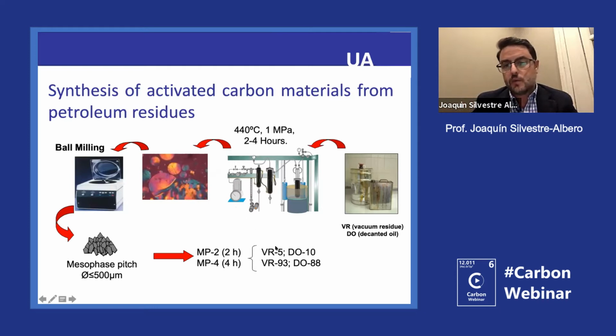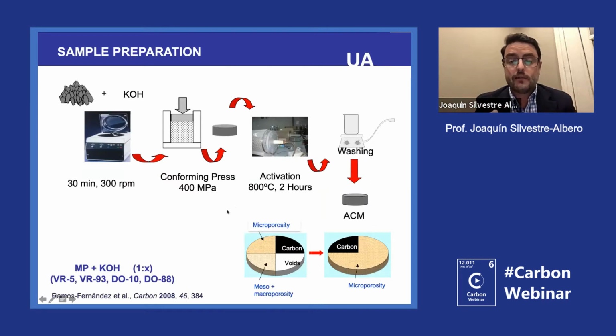So at the end, we were able to obtain residues with a low mesophase content, in this case VR5, that means 5% of mesophase, or changing the time conditions, we were able to go to high mesophase content. So we were preparing samples like, for instance, VR93, where you have 93% of mesophase. So basically what we were doing is changing the microstructure of the petroleum pitch, as I say, by modifying the pyrolysis time.